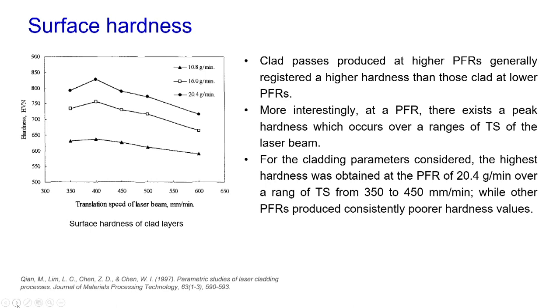In addition to the dilution and the clad profile, we can also study the surface hardness. The clad passes produced at higher PFRs generally registered a higher hardness than those clad at lower PFRs. If you notice, the higher PFR is 20.4 gram per minute. When we plot TS along the x axis and hardness along the y axis, for higher PFR values, the hardness is more.